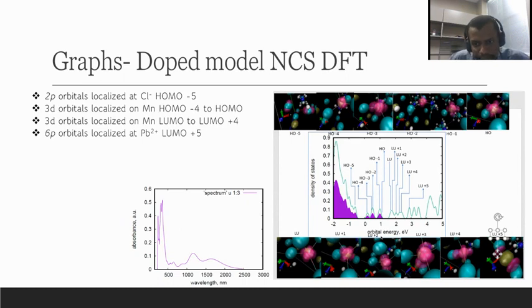So we can see from HOMO -4 to HOMO, from the orbitals at the top of this density of states, that the four last ones are localized on the manganese and look like the orbitals that we looked at earlier. But then the one before that is localized on the chlorine. That's the 2p orbital localized on the chlorine.